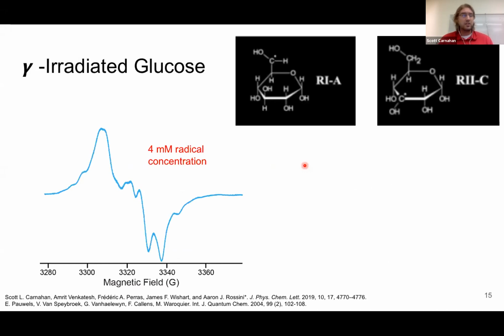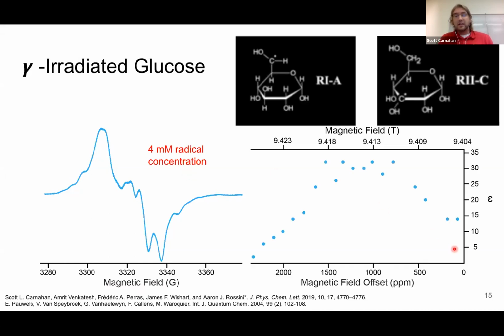Like I said, there are some other samples we're able to get this to work for as well, one of which is gamma radiated glucose. There are a couple of different proposed structures for gamma radiated glucose, both of which have the radical sitting on a carbon center. One thing we can see is that the EPR spectrum for glucose is much broader than that of quartz. There's some hyperfine coupling and a larger g anisotropy. We also have a higher radical concentration, about 10 times higher than that of quartz. When we do our field sweep, we also see that it's much broader. We're only able to get a partial field sweep for this one, and we can see that there's a broad match condition. Between the broad field sweep profile as well as the higher radical concentration, we're thinking that this might be through the cross effect, but it's a little harder to tell.